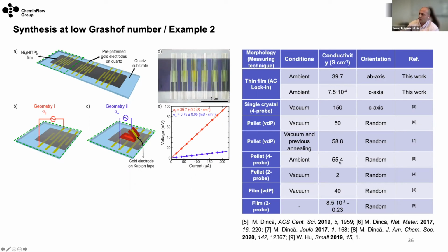But I would like to highlight here that to achieve this conductivity, they were generating pellets that were pressed at 1 gigapascal. So they had to apply huge pressures to achieve this value here. Our film has no treatment at all. It's generated and measured directly. So we have a direct integration of our film on these electrodes. And what is also very interesting is that in the c axis, so through the film, we have this ratio. It's similar to the one you observe in graphite.